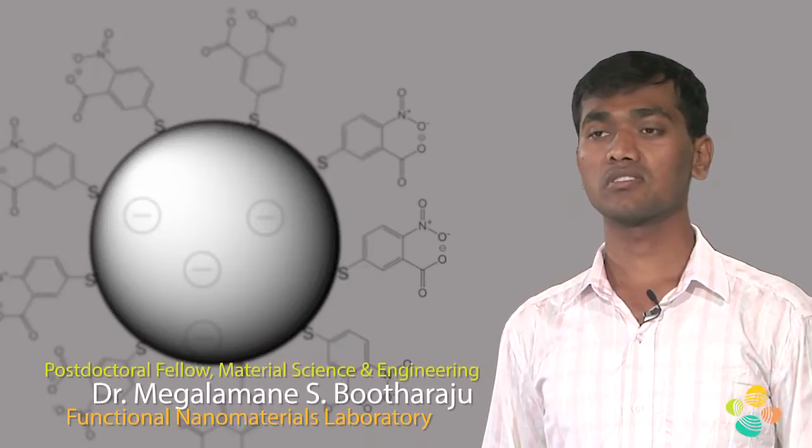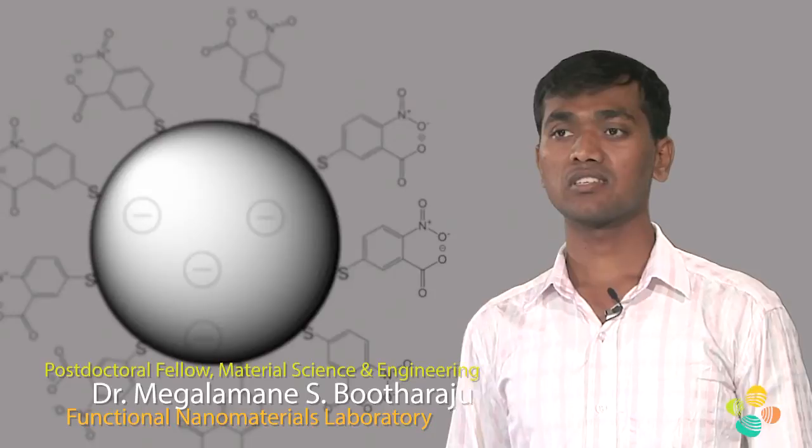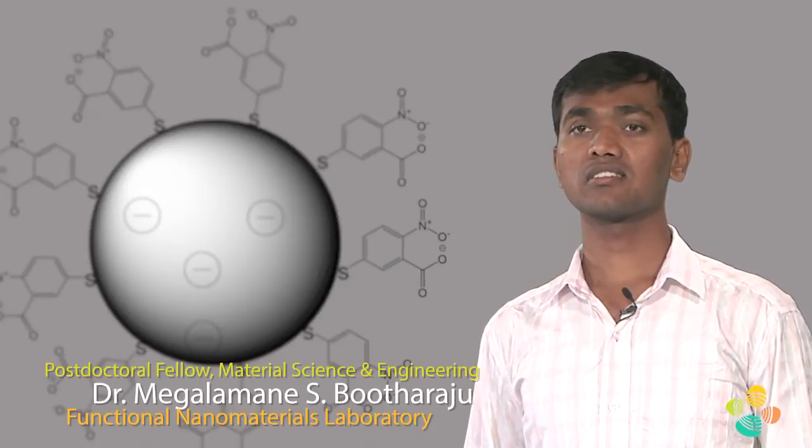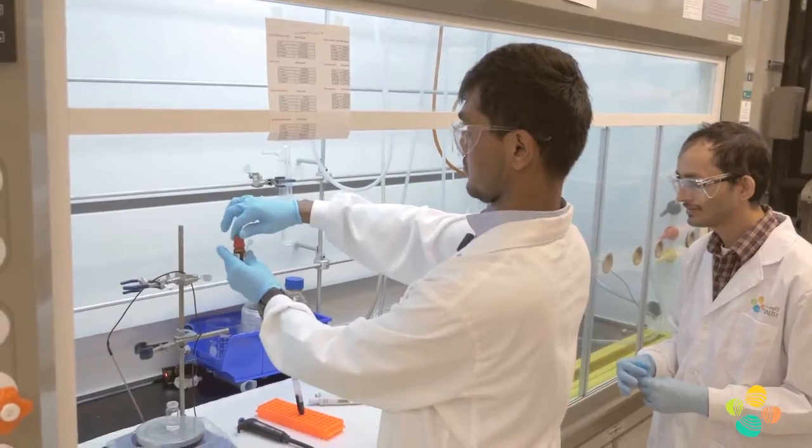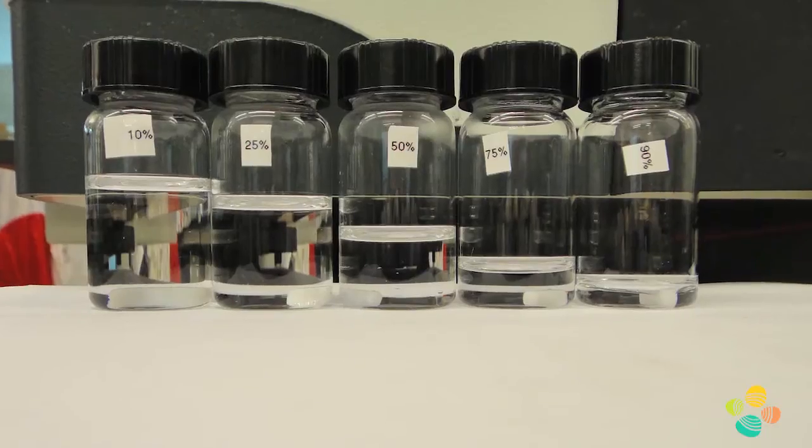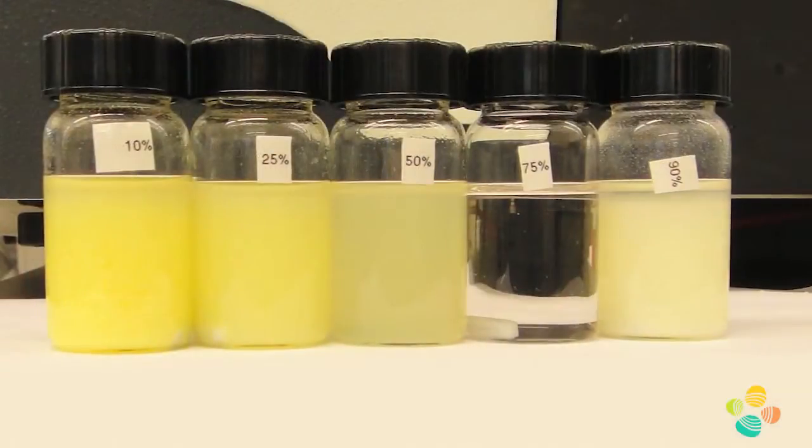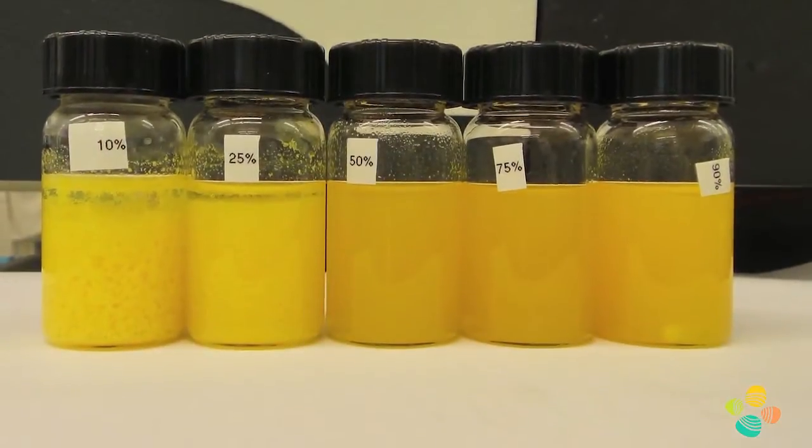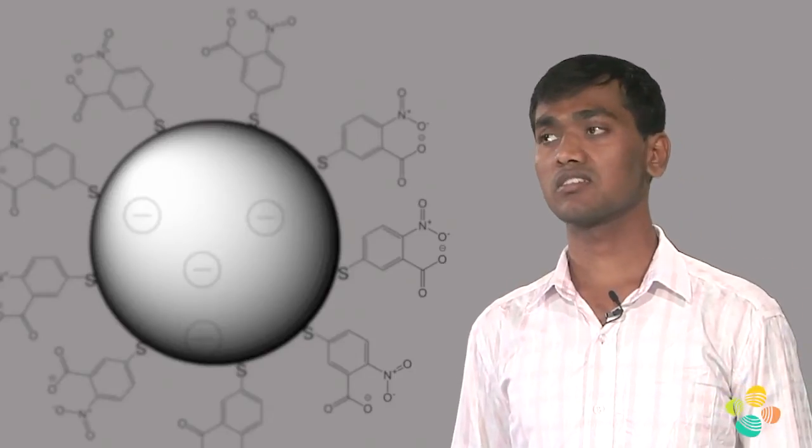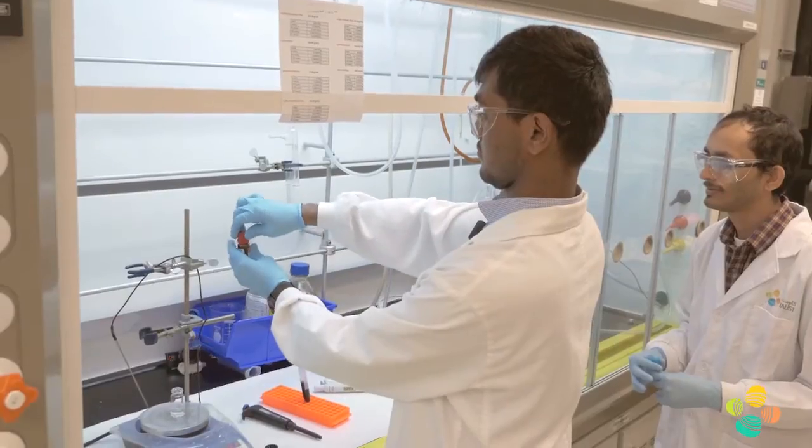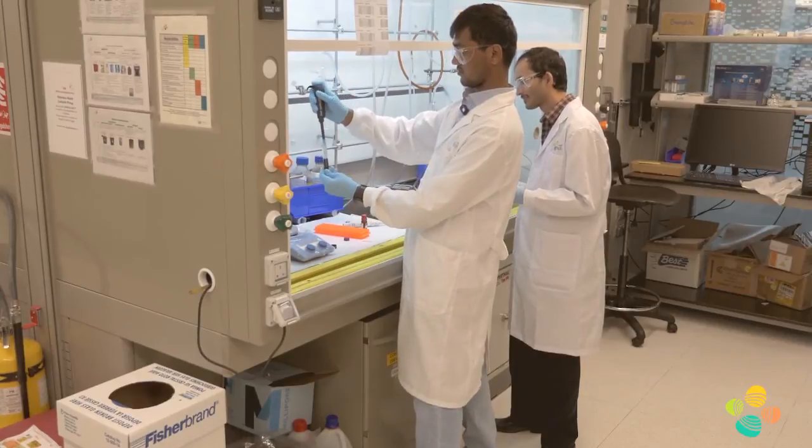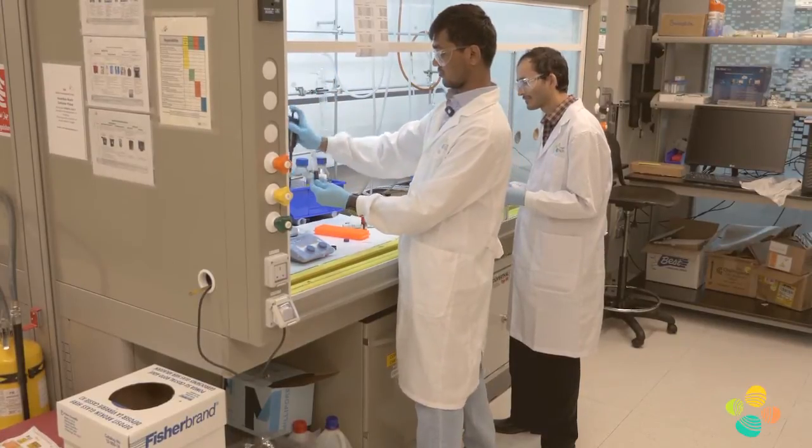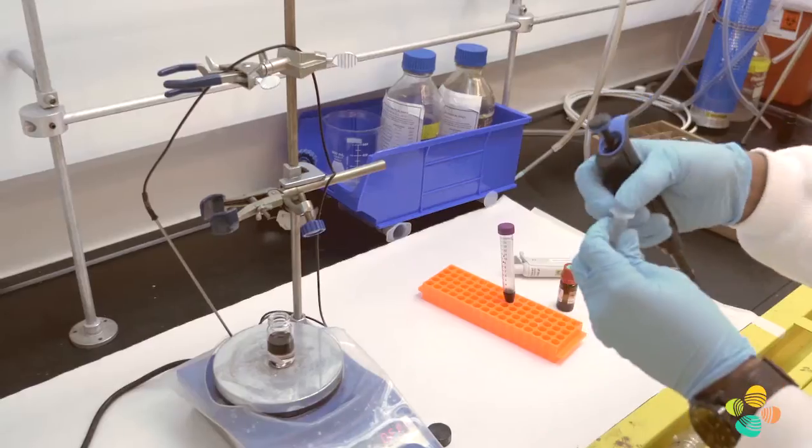My work focus is on silver nanocluster synthesis and its crystallization. For application purposes, silver nanoclusters or any other cluster needs to be processed in organic solvents. Cluster is water soluble so it's very difficult to process them for applications such as photocatalysis, catalysis and photovoltaics. In view of this we tried to exchange the ligands to transfer them into organics.